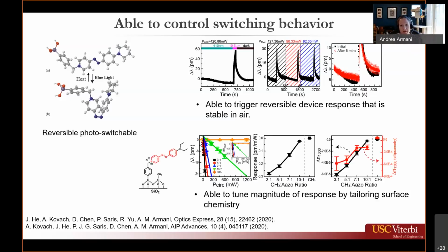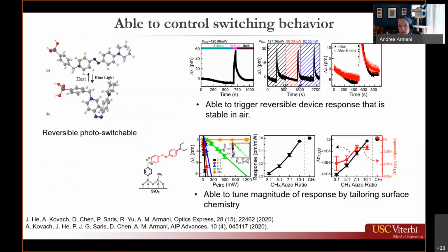We then made a series of devices where we varied the ratio of the methyl group with the photo-switchable molecule. And we showed that we could actually tune the response we got, and that the tuning actually varied linearly over the scale that we studied. And if we didn't have any kind of photo-switchable molecule, we basically didn't see any kind of response. And then when we compared the response that we achieved with a control system that we did with an ellipsometer, we got very similar results in terms of scaling.